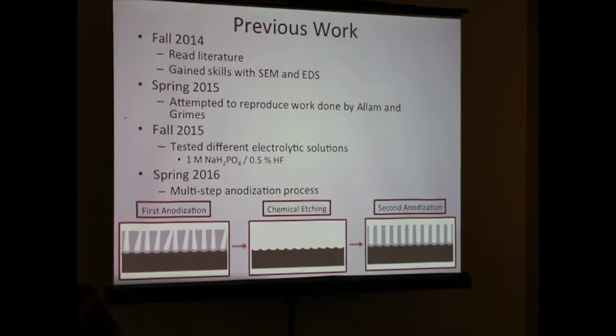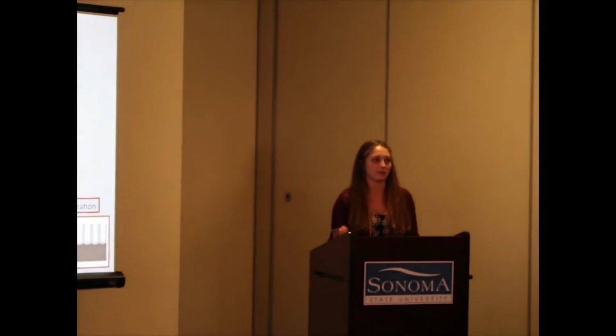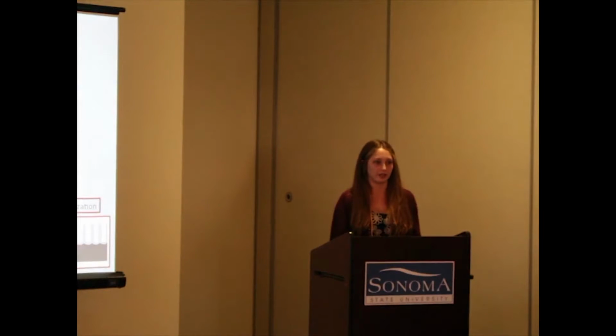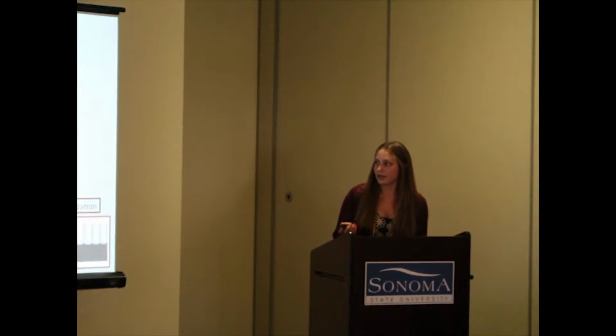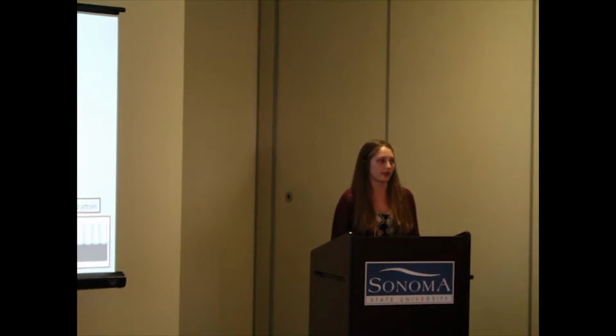From that, we went to the next semester, and we were trying different electrolytic solutions containing a little bit of hydrofluoric acid. As I mentioned earlier, it is a contaminant. It is bad for the environment. However, we were using a very small amount. Only 0.5% of our solution was hydrofluoric acid, and we reused our solution over and over again, so that way we would have less waste produced. During this semester, we found that a mixture of monosodium phosphate and hydrofluoric acid was the best electrolyte that would give us our ordered nanotube array.